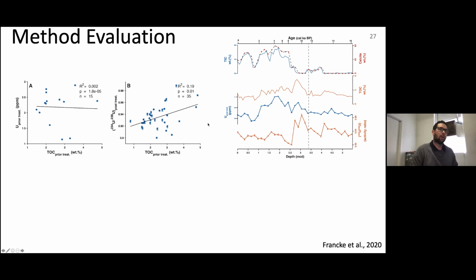What you usually expect, because organic matter-rich sediments usually have strongly reducing conditions, and uranium tends to be less mobile in reducing conditions, is that organic matter is usually enriched in uranium. So at many sites you find a strong positive correlation between uranium and organic matter content. We find that there's no correlation at all, which has also been described previously in the literature. And we then also looked into the comparison between the activity ratios before and after the treatment.